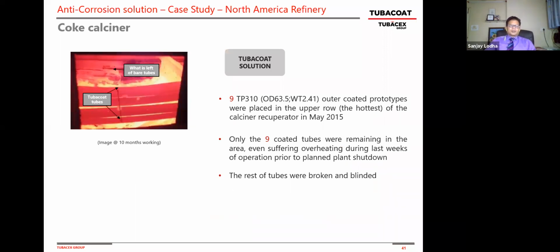So what you see here is we supplied some 9 TP310 tubes, outer coated in this recuperator heater. They were installed in May 2015, now almost 5 years ago. And after 10 months, when you see through a furnace window, what you see here is uncoated tubes are completely broken and blinded. You don't see them melted, whereas the Tubacoat tubes, all 9 of them are fully visible, even after suffering the overheating at temperature close to 1500 degrees Fahrenheit.